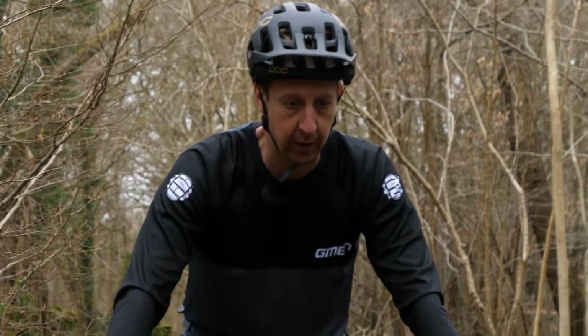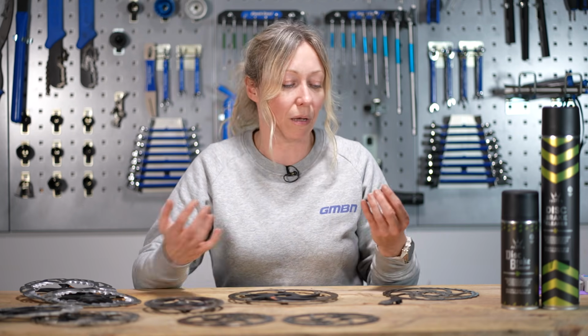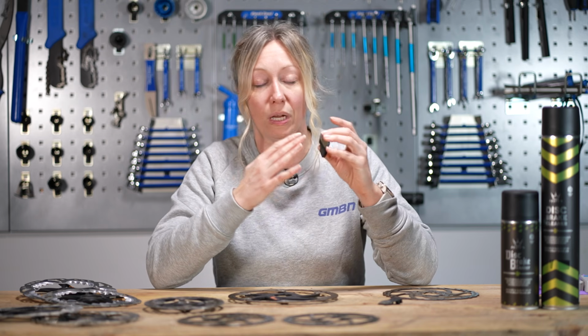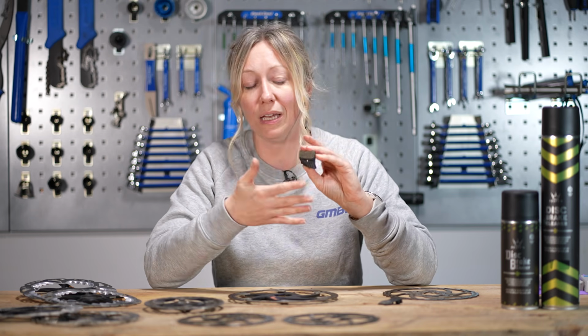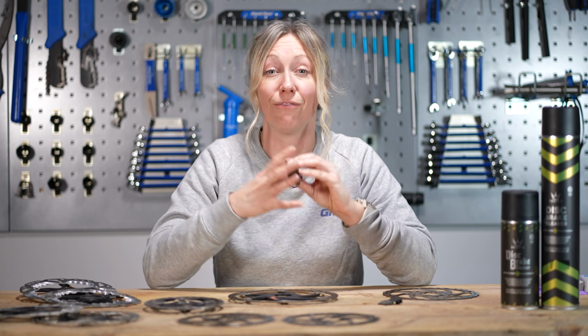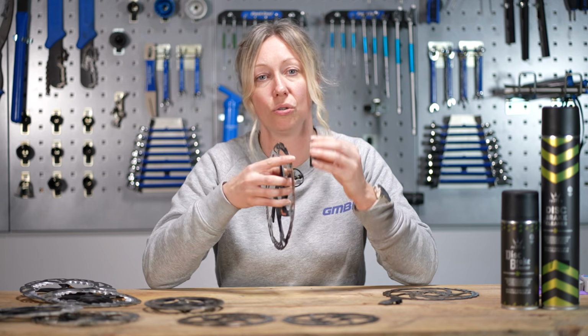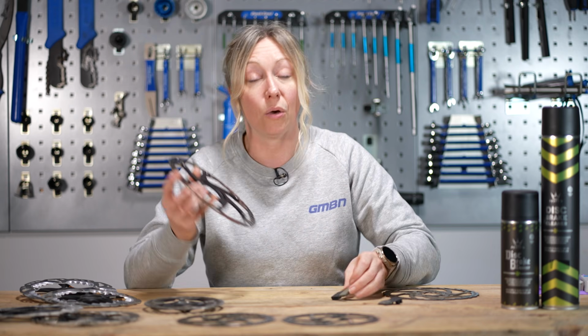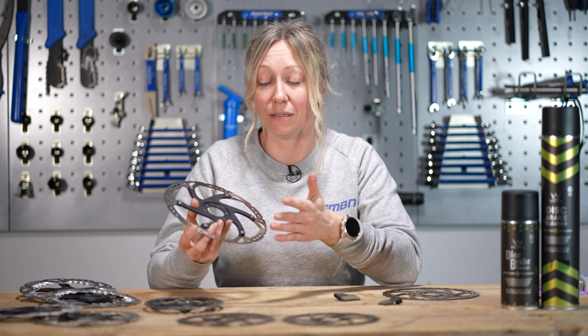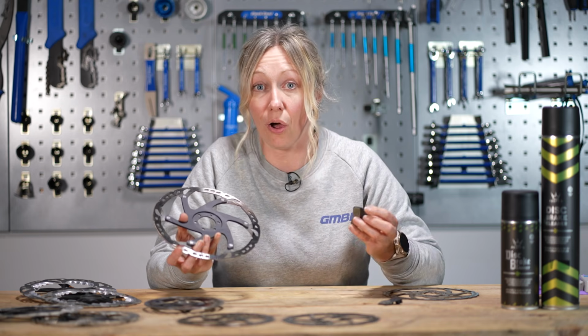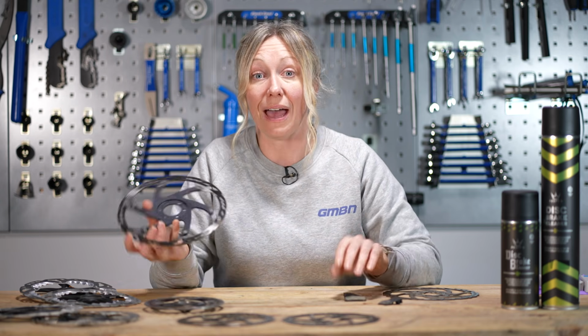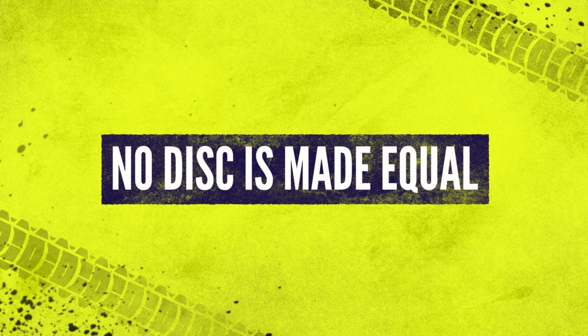But the idea is to do this gradually, to gradually deposit this material onto the disc. If you rush it, you could end up heating them up, say glazing them, which basically means you've created a shiny surface on the pad, and that won't grip. There won't be enough friction against the pad and the disc to create a good braking surface. Equally, you can actually glaze a disc. You can heat it up too much so that you get a nice shiny surface with no pores that can take on the material from your pad. So that's not optimum either. So do the process properly and take your time. Don't rush it.